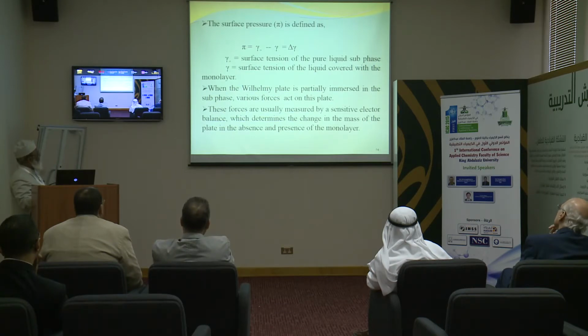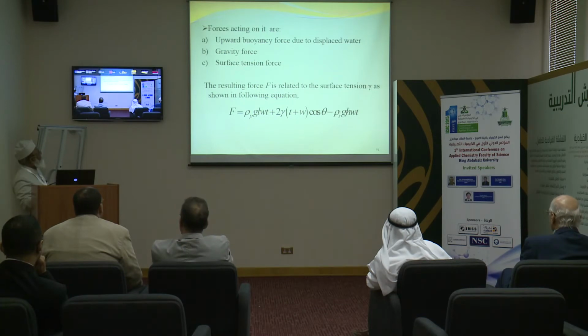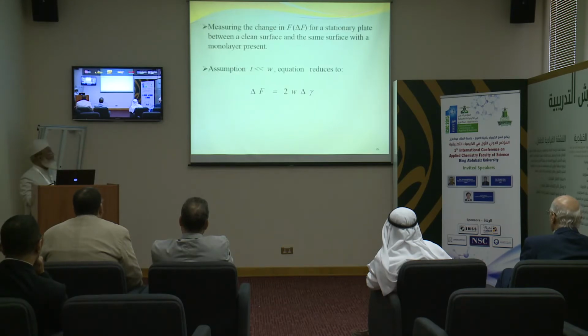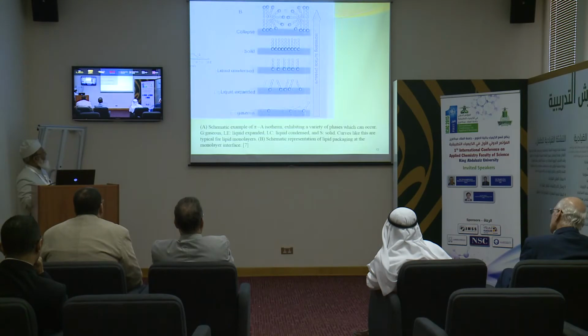This can be defined as the difference between the surface tension of the pure liquid surface, that is water, minus the surface tension of the liquid covered with the monolayer. So when the Wilhelmy plate is partially immersed in the surface, various forces act on this plate, and these forces are measured. They are the upward buoyancy force due to the displaced water, the gravity force acting downward, and the surface tension force, and we can make the force balance given by this equation. We can measure the change in the force for a stationary plate between a clean surface and the same surface with the monolayer present.